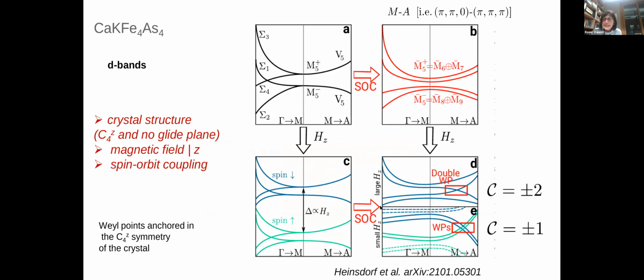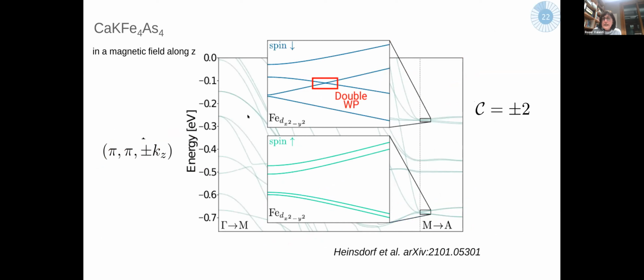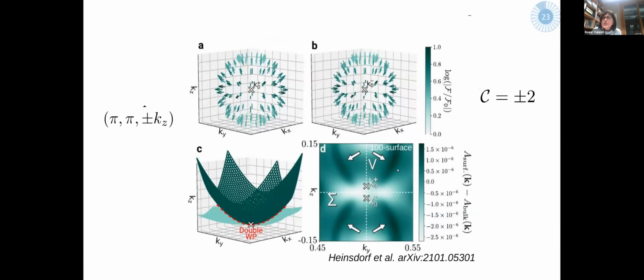Yes. So what I expect, if you put a large magnetic field, and then you are able to basically separate these bands so that you don't have a mixing of the two polarizations. Right. And now I'm showing it here. This of course depends on the features of your material, but in this material, if you put a magnetic field and you are able to bring this on the surface, by using the dope, you should be able, depending on the experiment you do. So if you do a transport experiment, you should be able, for instance, to see these effects of these Fermi arcs. If you do an ARPES experiment, the question is with magnetic field, I think there is no possibility, right? Right. So there is no way, but transport, yes. So one would see, in fact, a lot of anomalies in transport experiments.